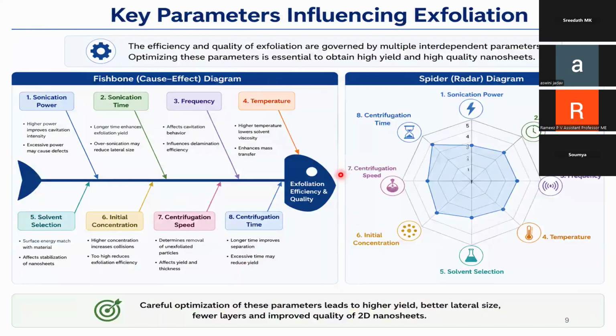So what are the parameters influencing the exfoliation? As you know, exfoliation is nothing but peeling of this material. There are several factors that govern the exfoliation: sonication power, sonication time, frequency, temperature, centrifugation time, centrifugation speed, initial concentration, and solvent selection. Solvent selection I already mentioned. We need to have the surface energy matching that of the material.